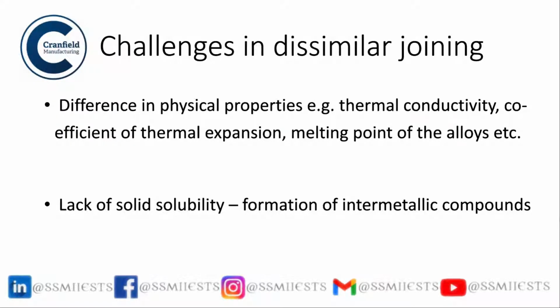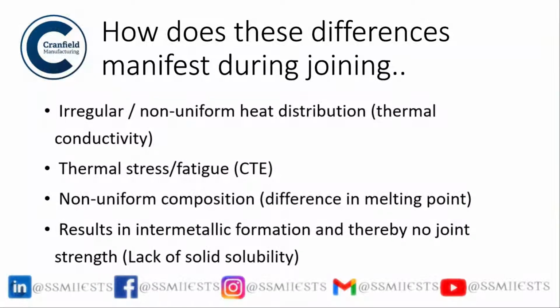So what are the challenges in dissimilar joining? There are basically two challenges. One is the difference in physical properties, be it thermal conductivity, coefficient of thermal expansion, melting points, and all these. The second one, which is even more complicated, is lack of solid solubility. This leads to formation of intermetallics, which are very brittle and can cause serious damage within a weld metal.